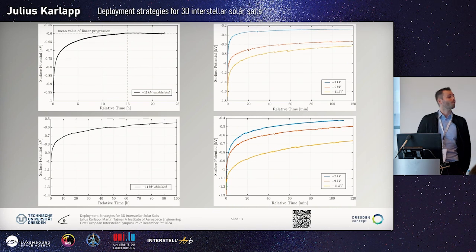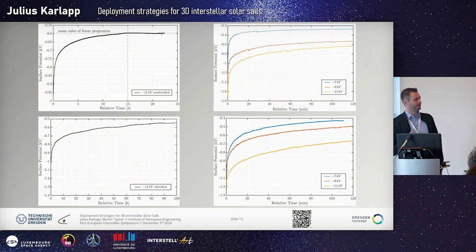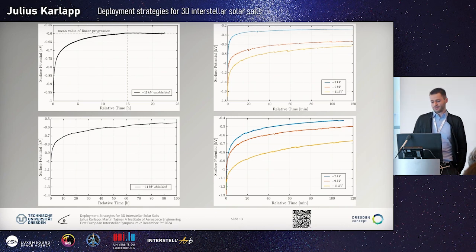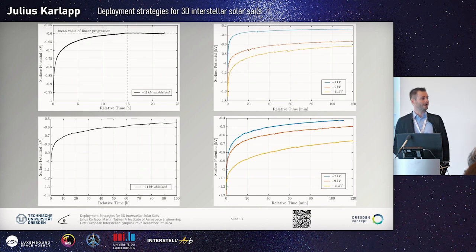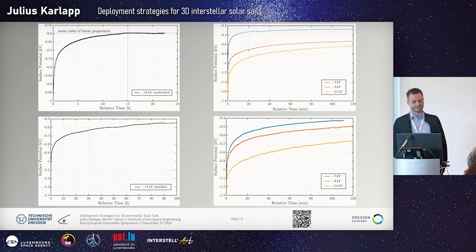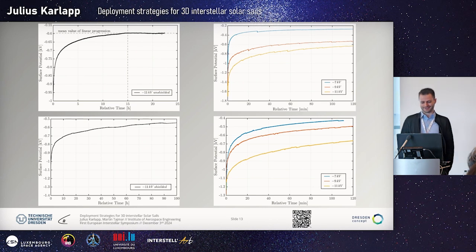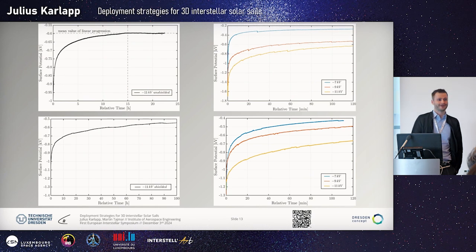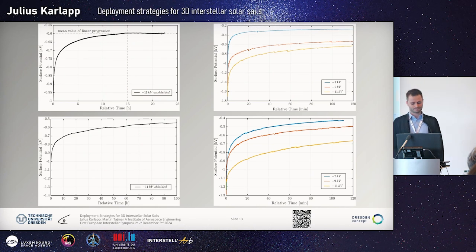We want to know why the surface potential is dropping. As we think so far, this is due to atmospheric ionization. So our next step would be to get into vacuum and repeat the experiments under vacuum conditions. This will happen in the next couple of months and hopefully further improve our electrodes and eventually help us validate the Coulomb deployment strategy.